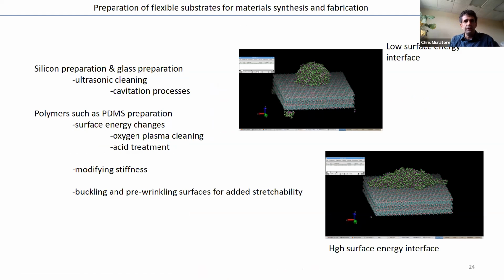Working with polymers can be a little bit of a challenge if you want to apply materials to the surface. So in general, polymers have low surface energies. And when materials have low surface energies and you want to attach something to the surface, it tends to ball up or not wet on the surface. Sometimes when you want to use polymers as a substrate or for actual material, like let's say you want to put contacts on your semiconducting polymer, you may have to change the surface properties of that polymer to get better adhesion and contact of the metal onto the surface.